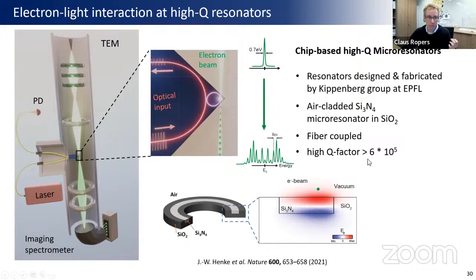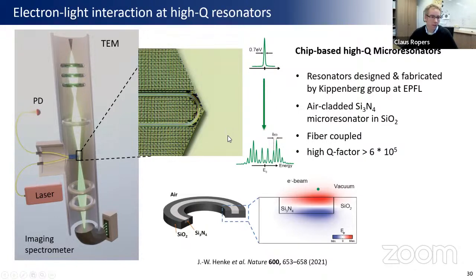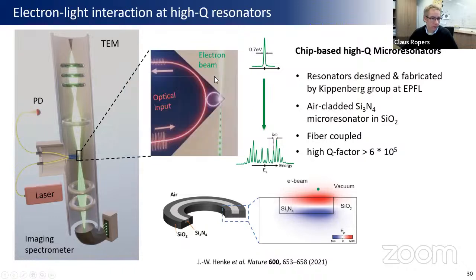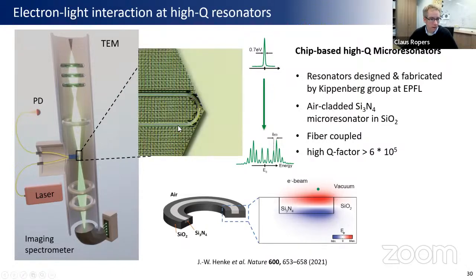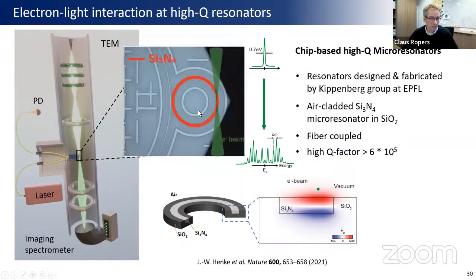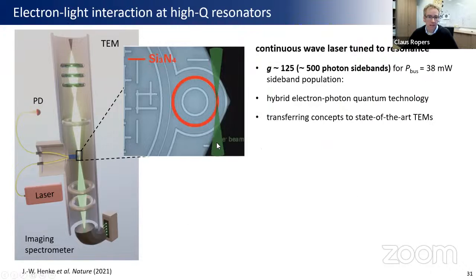Yeah. So what this means is you have a quality factor of 10 to the 6, you couple in only 1 milliwatt, so a small laser pointer power essentially, into this waveguide. Then within these cavities here, you transfer this into 1 kilowatt. And this 1 kilowatt is actually sufficiently high field strength to very strongly affect the electron energy spectrum and modulate in energy the electron beam. Yeah. So here's an optical microscope image of these structures. So this is the waveguide. This couples into this high quality ring resonator, and you pass the electron beam through the optical near field and then again measure the kinetic energy spectrum.